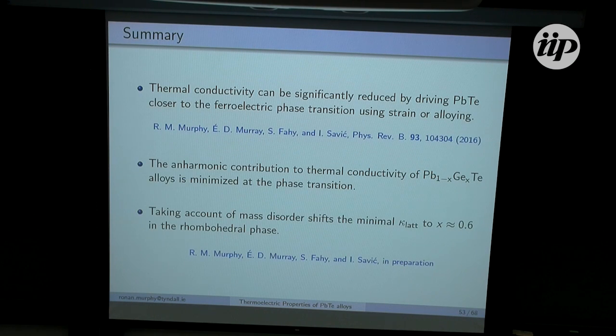So I just want to take this moment, before I move on to the final part of the talk, to briefly summarize a few of the main things I've shown you from this section. You saw that for lead telluride, and lead telluride alloyed with lead selenide, by driving them towards the verge of this ferroelectric phase transition, we can substantially reduce the lattice thermal conductivity. And just as I showed you, in lead germanium telluride, the anharmonic contribution to thermal conductivity is minimized at the phase transition. Once you take into account mass disorder, that minimum actually shifts into the rhombohedral phase. But again, because you're combining the effects of mass disorder with increased proximity to the phase transition, you get quite a substantial reduction to that.